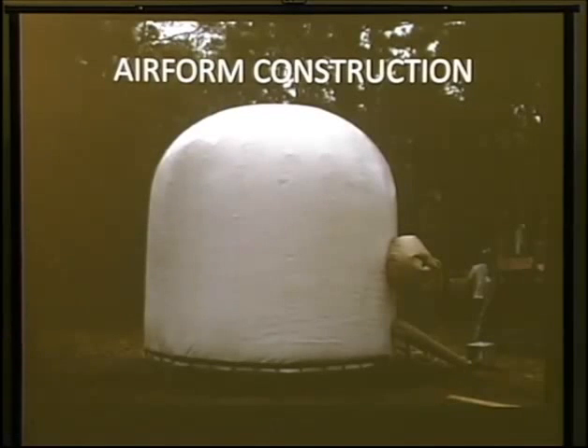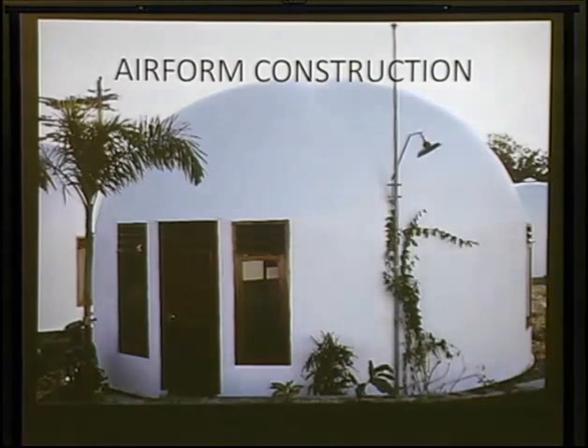Now, the method of construction I would propose is using inflatable airforms like this, which we use on Earth. This is just an example of an inflatable airform. And there's a structure built from a small house built with airform construction. The way it's built is you inflate the airform and just simply place zero slump or low slump concrete on the outside and let it dry. Then, once it's cured, you deflate the airform, peel it off the inside, and reuse it.